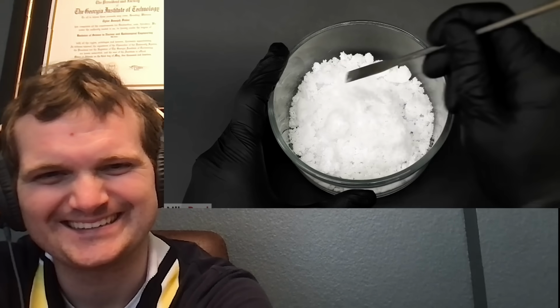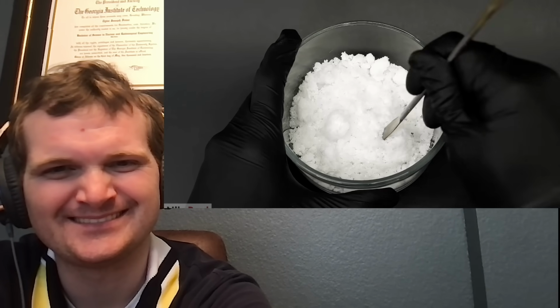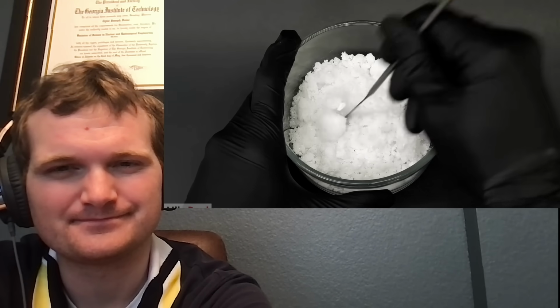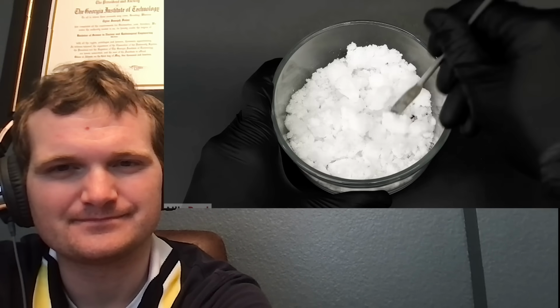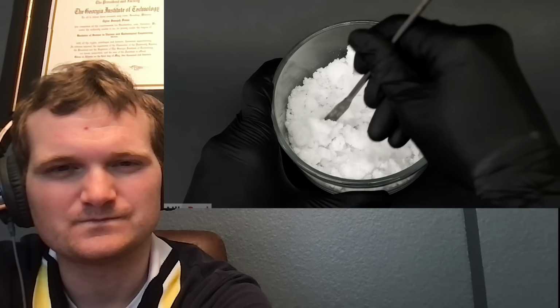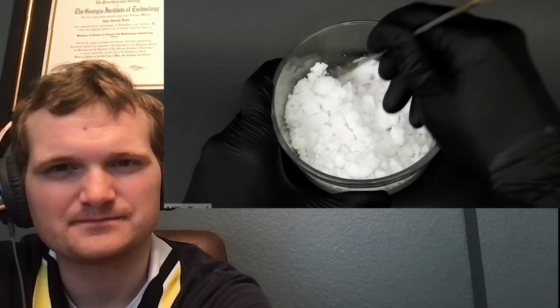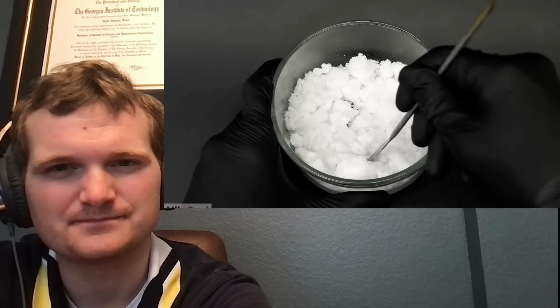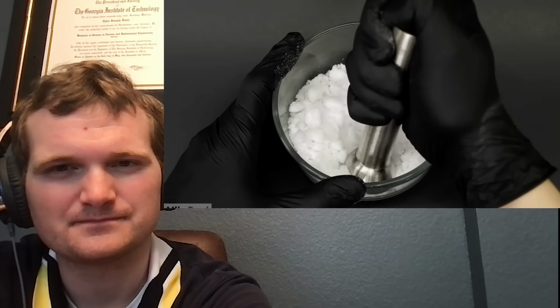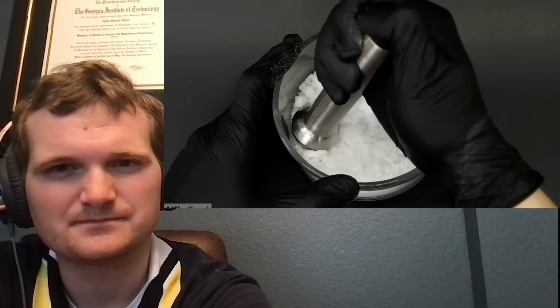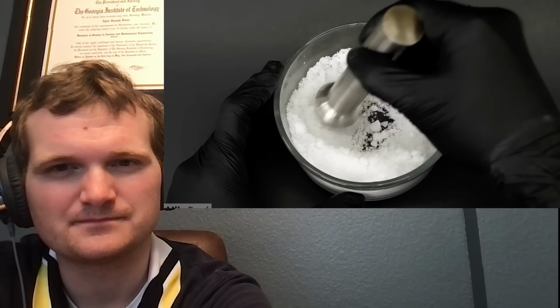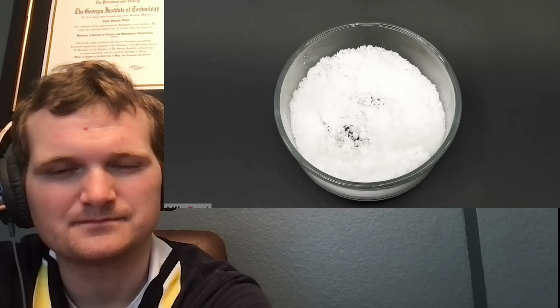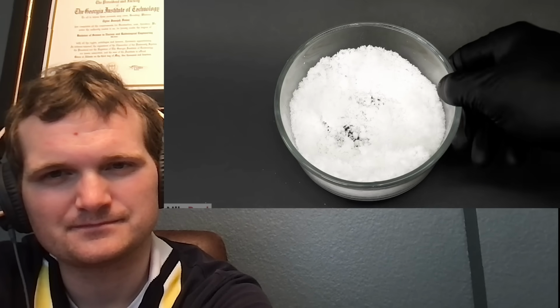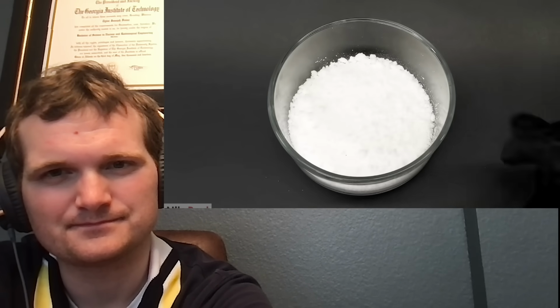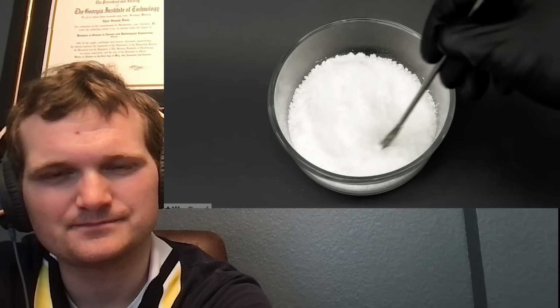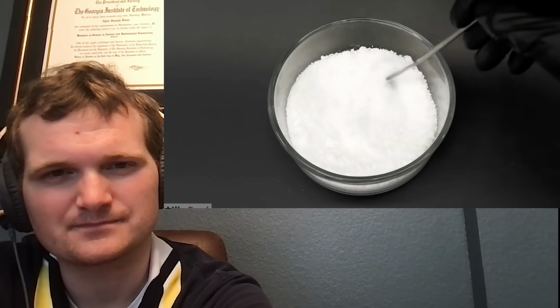This of course wasn't the oxide that I had started with, and if I specifically needed it to be the oxide, part of the purification process would have been converting it back. But conveniently, turning the oxide into the nitrate is actually the first step in a lot of YBCO procedures, including the one that I was following. So, this whole purification was kind of just a slightly more complicated first step. At this point, it was still a bit wet, so I put it all back into the vacuum chamber and I let it dry for a few days. After this, I had some dry and pure yttrium nitrate, and now I could actually start making the YBCO.